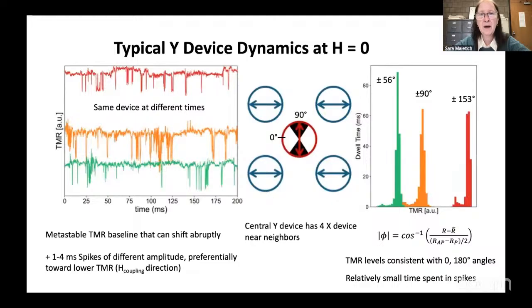If we look at these Y devices, which will have 4 X nearest neighbors with magnetic moments jumping back and forth perpendicular to it, we saw a real surprise. Looking at the same device at different times, the resistance could be this red curve showing some spikes to lower resistance, but then a few seconds later, or hundreds of milliseconds later, it could jump to a different level. Same device, just jumps to a different baseline, jumps to a third baseline, jumps back and forth, but is fairly constant other than these short excursions, mostly to lower resistance.